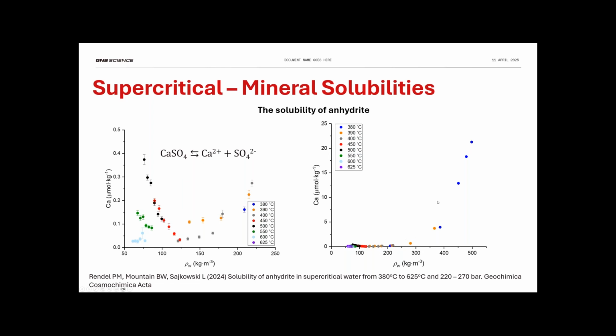So you see the maximum solubility we got was at 380 degrees, and that was about 800 ppb. So this represents about 800 parts per billion. So you can see the solubility of anhydrite is pretty darn low under these conditions. So I wouldn't expect much to dissolve, but I wouldn't expect much to be able to be carried in solution either. It's interesting because when we go up to higher temperatures, the solubilities actually start to go up.